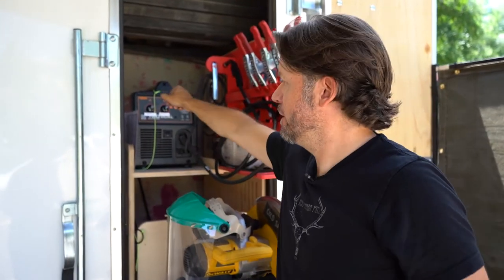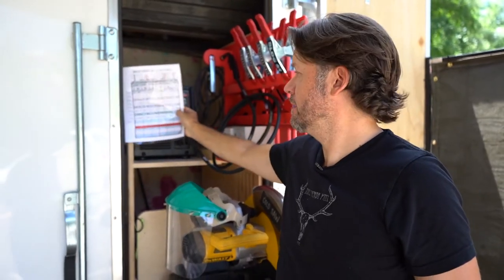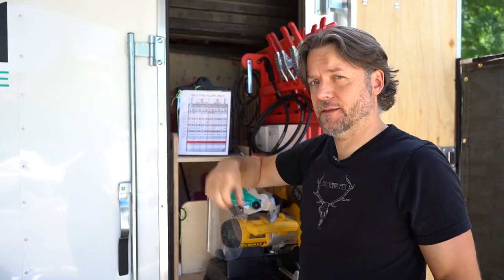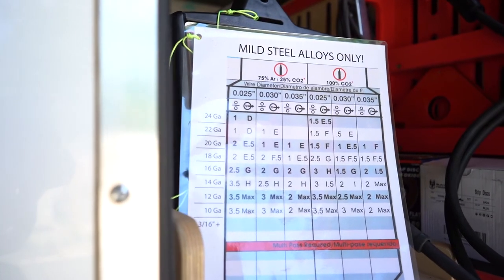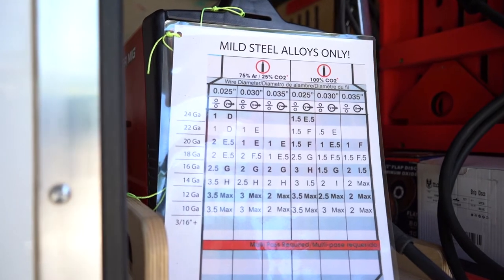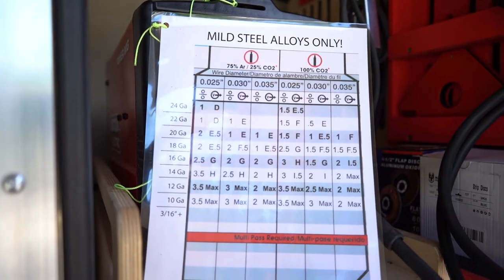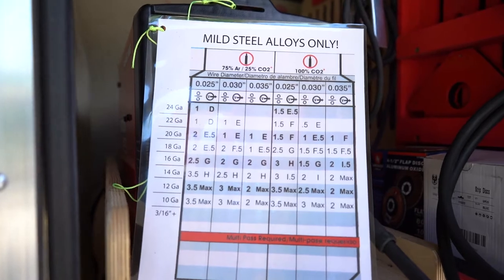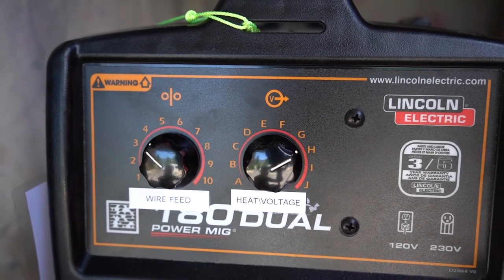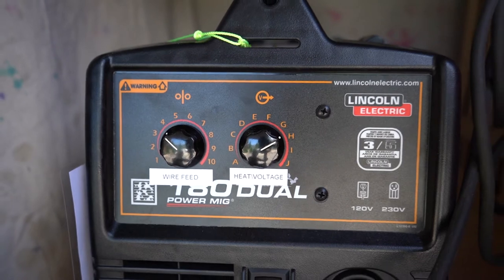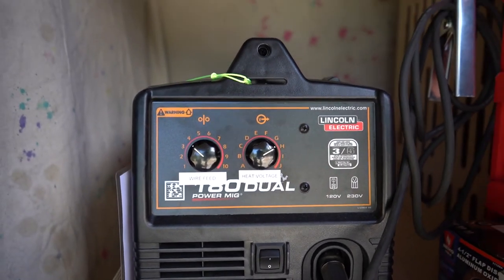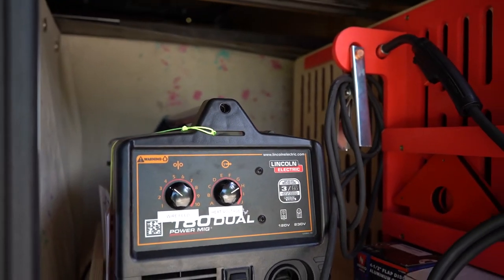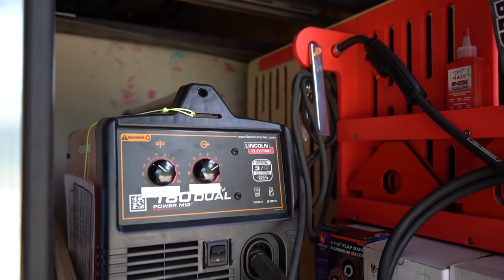To use this chart, we need to know our gas mixture, our wire thickness, and the thickness of the metal referred to as the gauge. Unless otherwise stated, Building 61 will use a 75/25 argon CO2 gas mixture, an .035 wire. So to weld my stock material of 12 gauge steel, we'll set the wire feed to 3.5 and the power to position H, which I'm assuming stands for hot as heck. Typically, we'll adjust these settings as we go, based on the observed results.